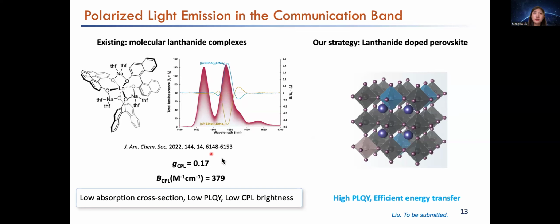So the existing material can reach the dissymmetry factor 0.17. I have seen an even higher number around 0.6 to 0.7. But the drawback of this material is they have very, very low absorption cross-section and low quantum efficiency, which means although they have a good degree of polarization, their brightness is very low. This is still not very good for using as a light emitter.